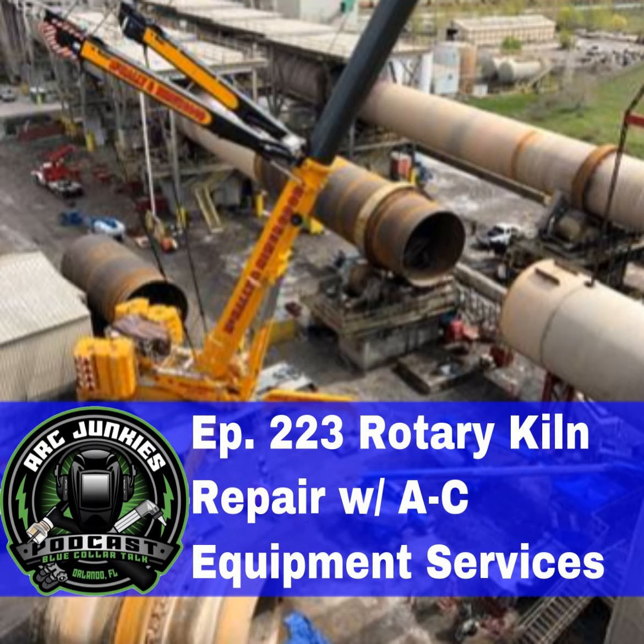And you can imagine we probably can't rotate any more than maybe 8 to 10 inches a minute when you're cutting real thick shell. Besides cutting with torches, we do a lot of air arcing to remove previously welded-on hardware. When we do put the new shell in and we fit the joints up, and seal pass it with flux core wire, we'll come back and use SAW submerged arc welding to weld 100% of it from the outside. We do that the same way we do the cutting: hold the subarc still, rotate the kiln, and subarc it at the 12 o'clock position. After the outside is welded, we'll go back to the inside and air arc back gouge into the good subarc weld, and then we'll flux core weld the inside till we have 100% weld.